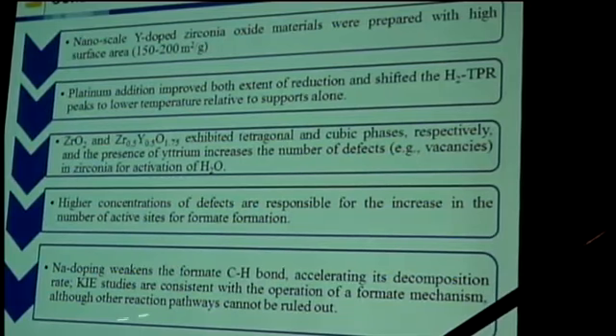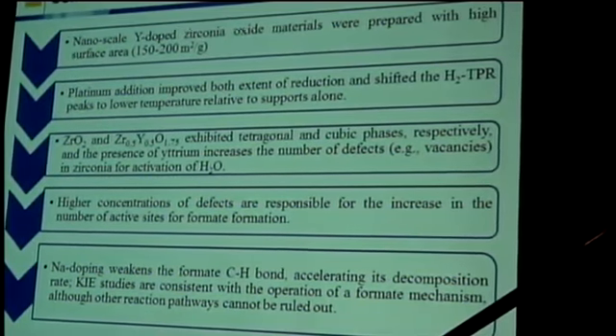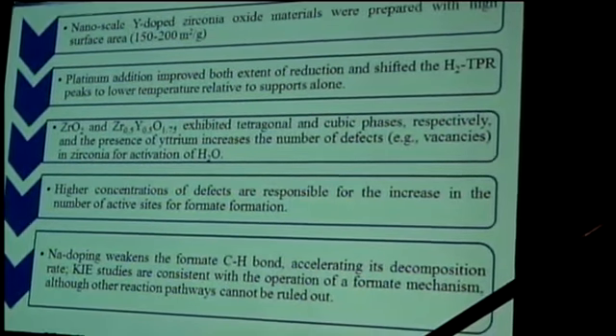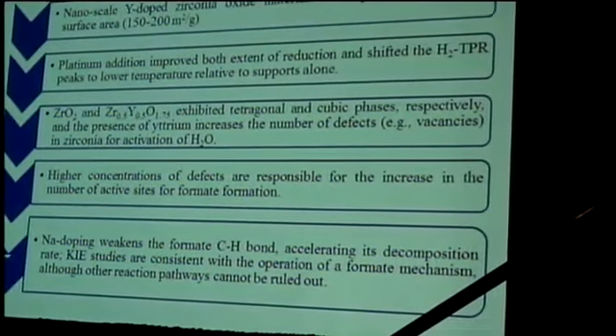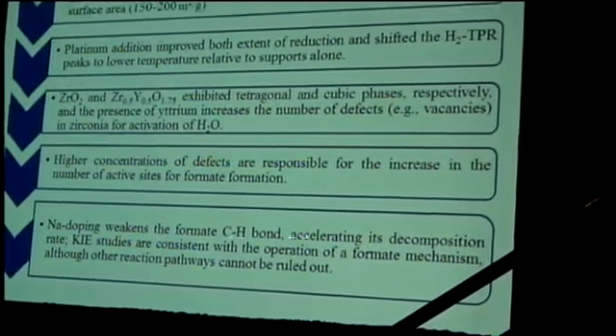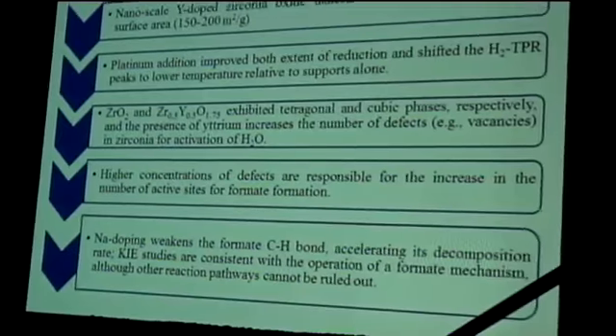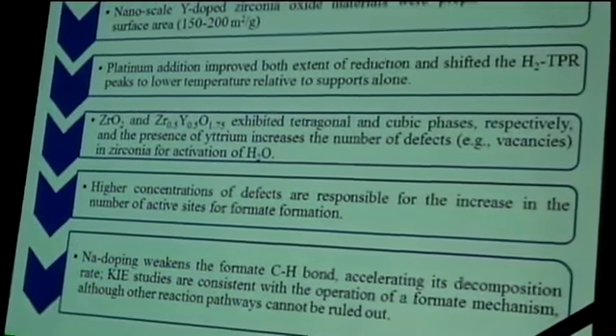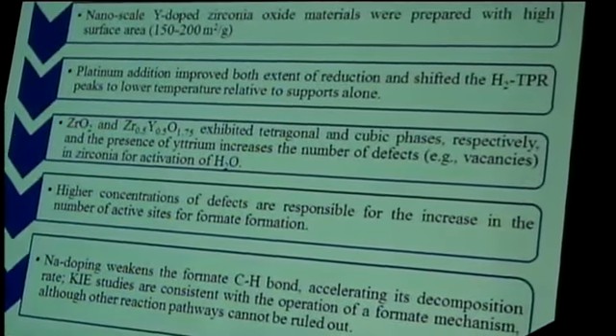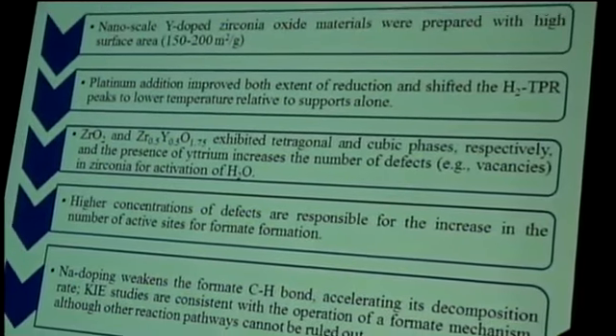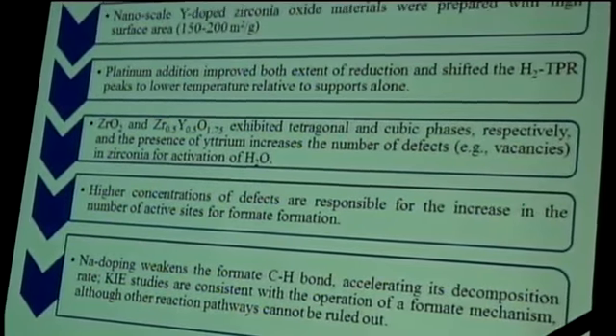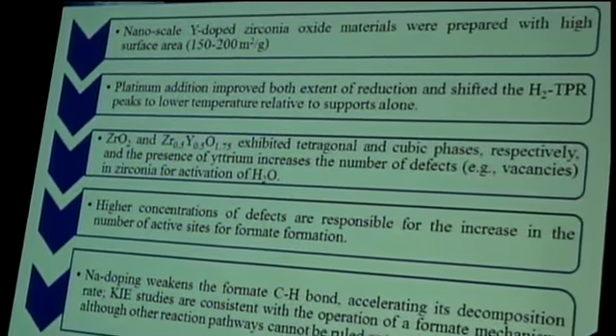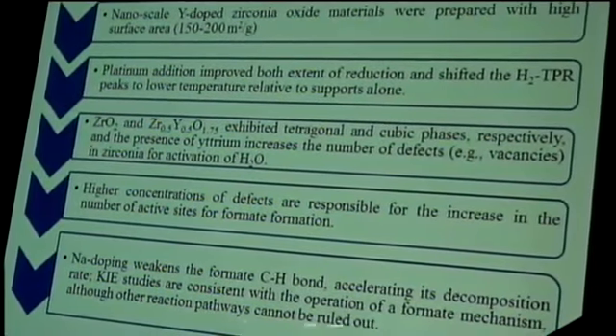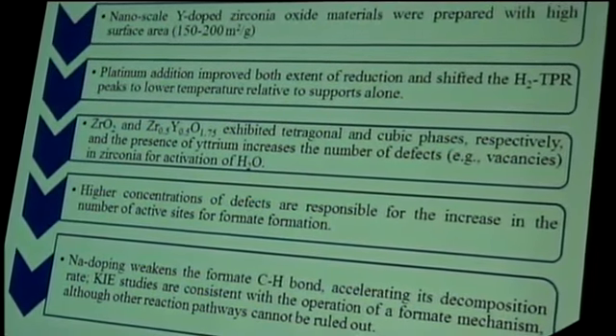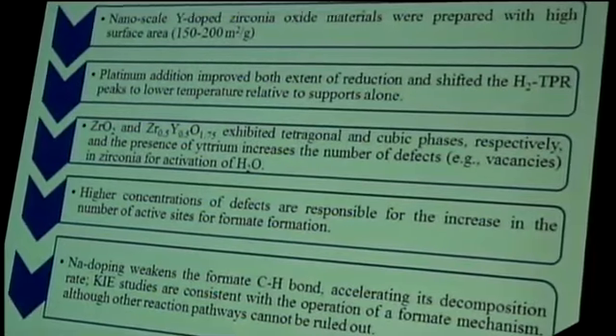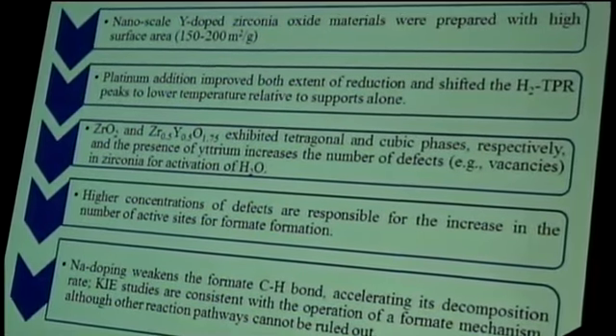The effect of sodium doping is very different. It seems to be an electronic modification leading to a weakening of the formate CH bond, and that accelerates its decomposition rate. And the kinetic isotope effect studies that we carried out are consistent with the operation of the formate mechanism, although certainly other reaction pathways could also be occurring and cannot be ruled out.